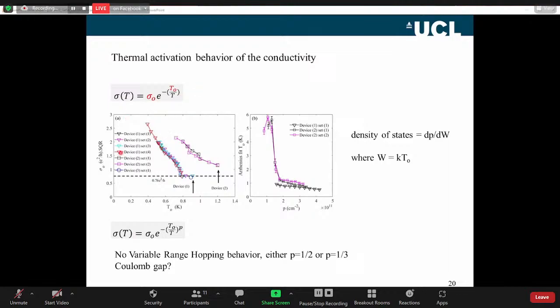And if we plot those parameters out, I've plotted sigma naught out against T0. There are a lot of measurements here, 3, 4 sets, 5, 6 sets of data on different devices, different cool downs, and we see a fairly universal behaviour. I'm pretty convinced this is a universal behaviour. Sigma 0 comes down to 0.76 e squared over h. This is very, very close to the Mott minimum metallic conductivity level predicted by Mott.